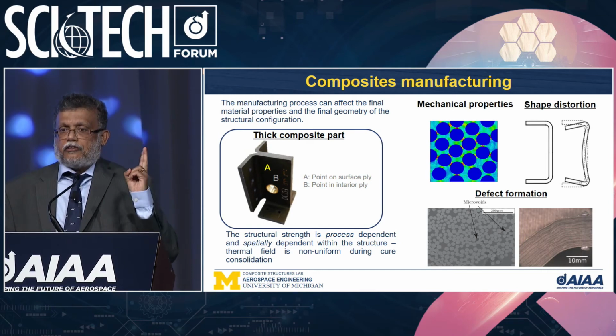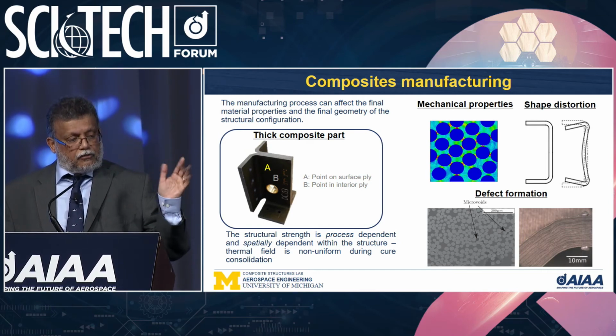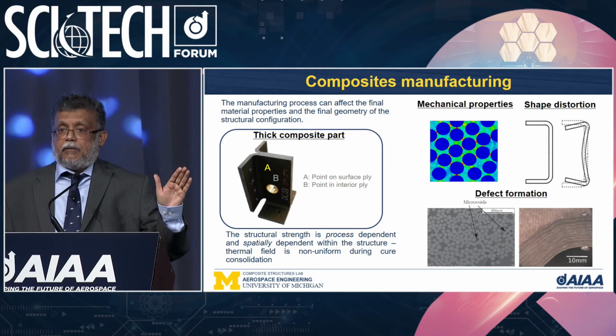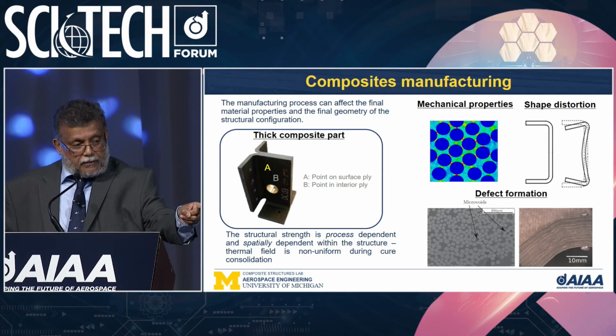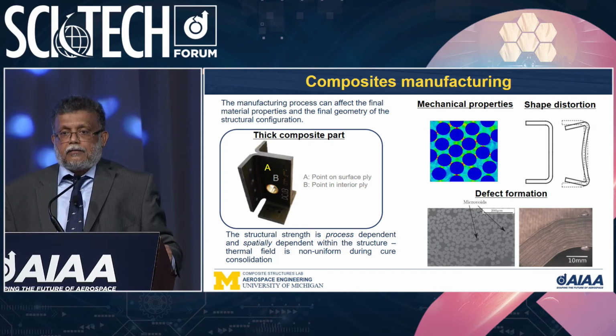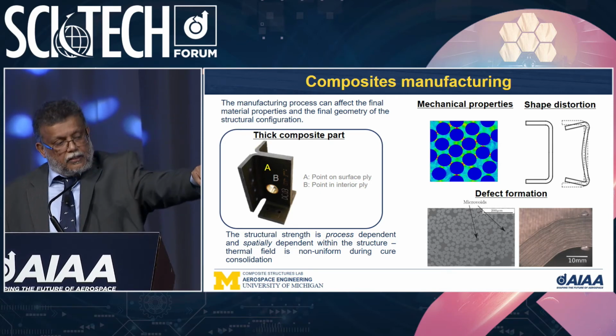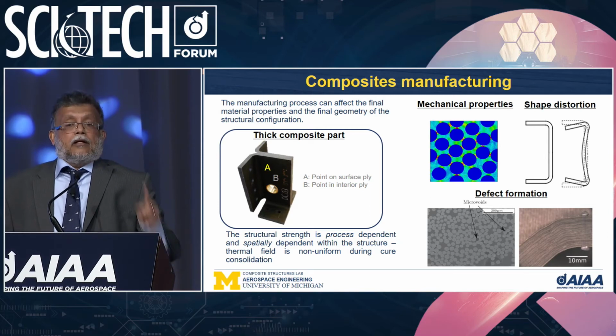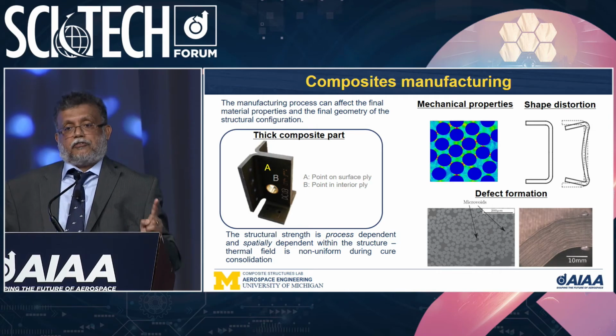If you take two points, one point A on the surface and another point B in the interior—now that is a 120 ply thick part, so there's 120 plies in the thick section—there's no way that the temperature distribution is going to be uniform during the autoclaving process.